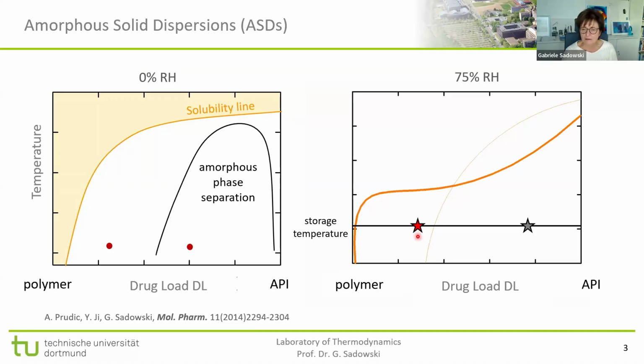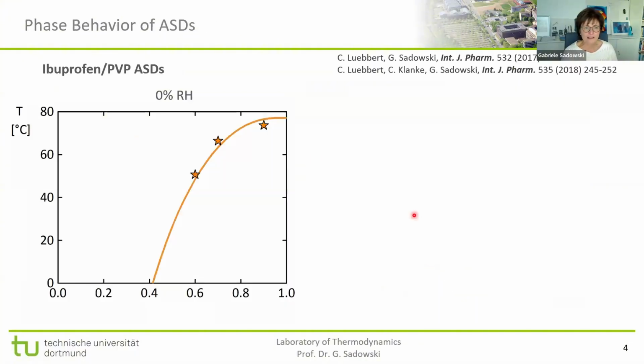That is something one would like to avoid, and so that means we need to know how the phase diagrams look in the absence or presence of water. And this is what we did. So, for example, this is for a dry system, ibuprofen, which you know is a nice API, and this is a polymer which could be used for formulation of tablets. And the advantage of PVP is that it has a high solubility for a lot of APIs. So what you see is this as data points we have measured, and this is our modeling using PC-SAFT,